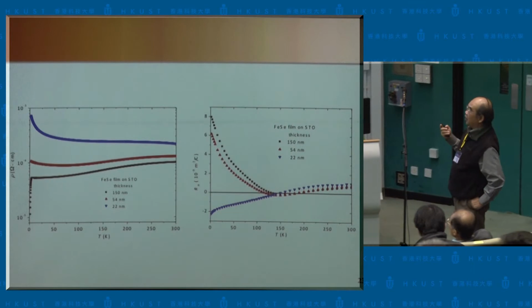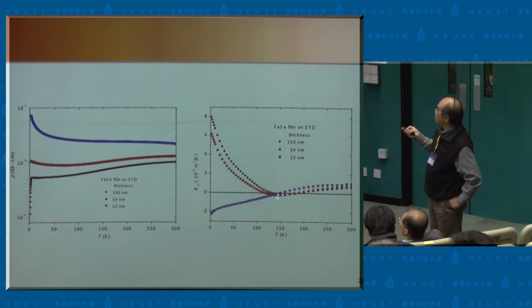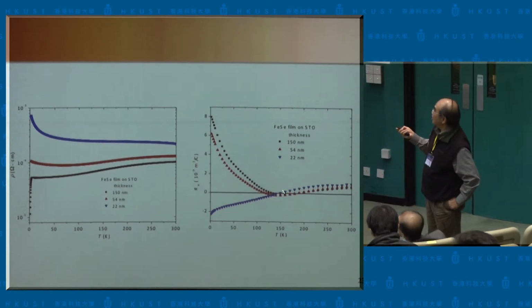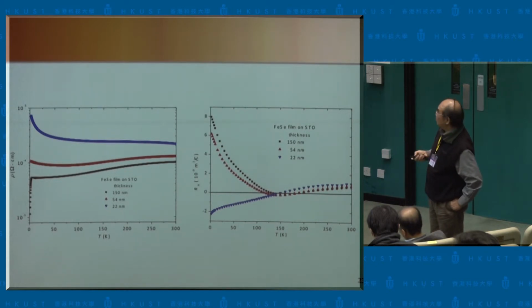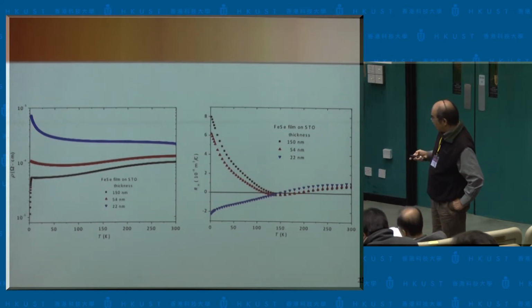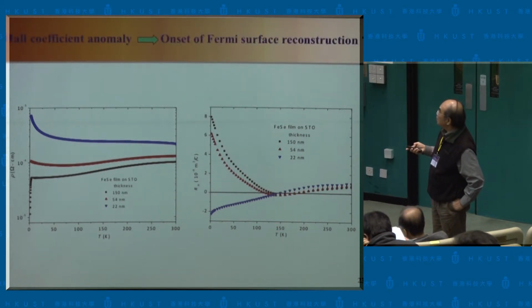And for the Hall effect, that is also similar. There is a feature indicating some kind of electronic structure change around 140 or 150 Kelvin. Okay, and this is from all these superconducting ones. For the non-superconducting one, you don't see that kind of behavior.